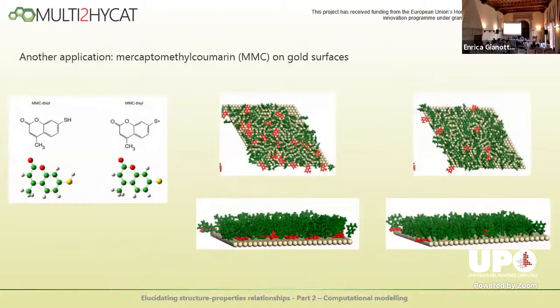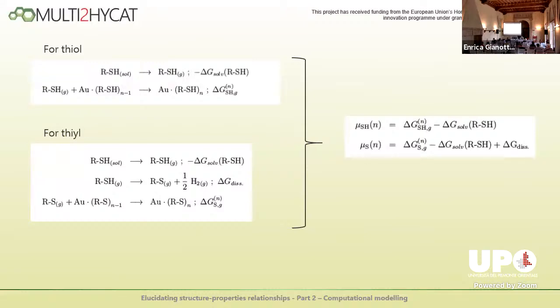And very quickly, an analogous application is in estimating the free energy of formation of a monolayer of thiols on top of metal surfaces. We want to compare thiols with SH or thiolate, I mean the radical you get when the hydrogen is eliminated. The two systems form different monolayers on the metal. To do this process, we had to split the formation process in several steps. For example, get the thiol, put it in vacuum, so desorb the thiol from the solvent, and then form the monolayer. Or in the second case, get the thiol, put it in vacuum, detach the hydrogen, and then form the monolayer. For any step, we can compute the delta G.